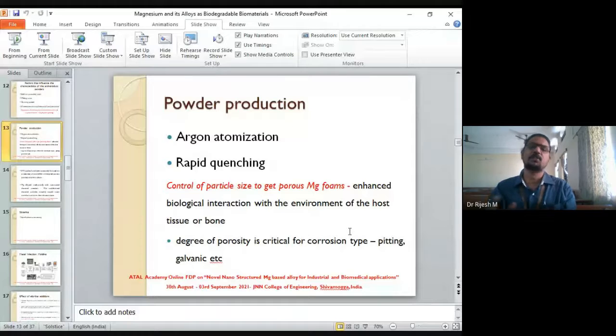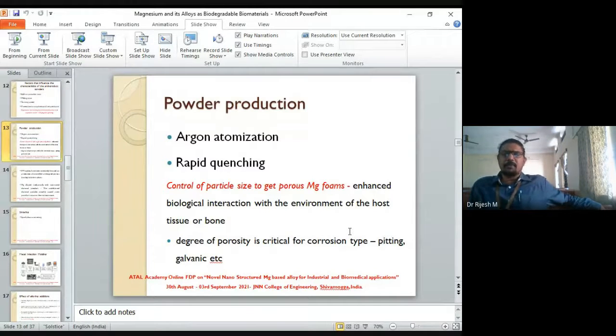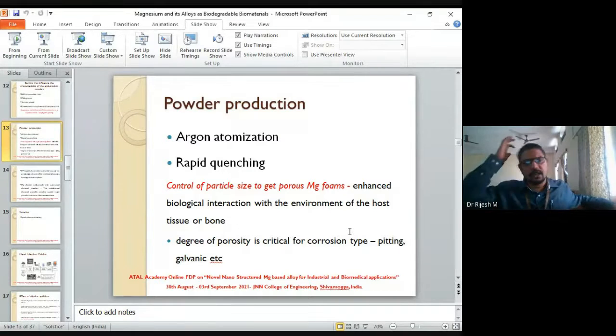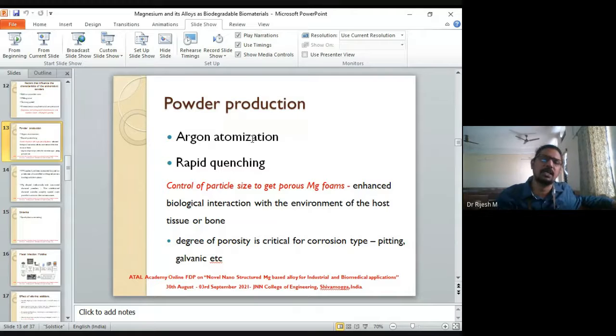In powder metallurgy, the first step is production of powder, and in many applications we have seen powders produced by mechanical ball milling, magnesium powders by mechanical ball milling, and not by conventional atomization, because melting magnesium is a very risky job. Magnesium tends to explode at higher temperatures. So we generally do not go for melting and atomization. Atomization is a process, but there are some applications where we go for it too. You heat at a very high temperature, melt the metal, and allow it to pass through a small orifice and rapidly quench it in some media. When you rapidly quench it, the droplets take size and shape and become the powder.